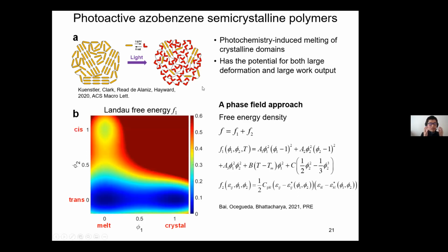So now what we can do is understand this mesoscale process again, using some elasticity model we had before. But in this case, we used a phase field model approach. So we can give the free energy density of this material. This F1 part is basically a phenomenological Landau free energy. And you can see it has a double well, actually a triple well structure, because now I have to take care of both trans and cis and also melt and crystal. So I have two other parameters, and trans is in the lower energy state, and melt and crystal follow this first order energy well. So these are taken care of in this mathematical model.